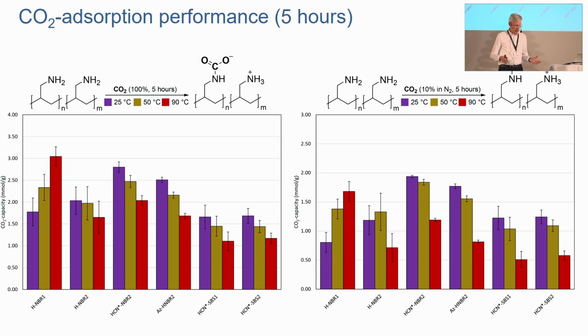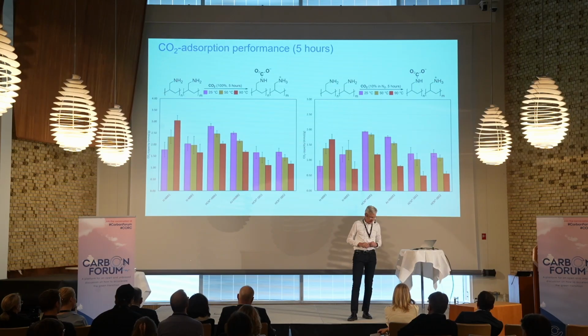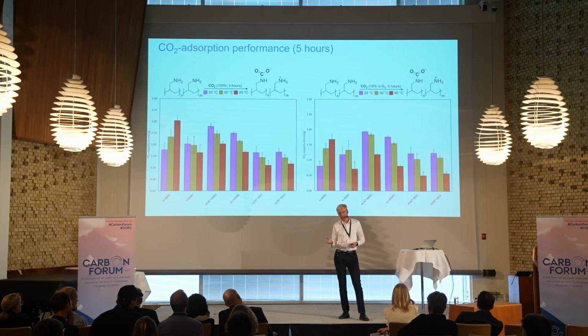So that was pretty good, but it falls short of the best known materials. What are the materials that we're comparing with? One is the MOF, the Metal Organic Framework, CALF 20, which is on the top line, at about 4. So we were underneath the state of the art in those types of materials, or it has another mechanism. But let's just say what is out there being scaled up. We also look at 10% CO2 in a nitrogen carrier gas, and again we'd expect it to be slightly lower, and that's exactly what it is.